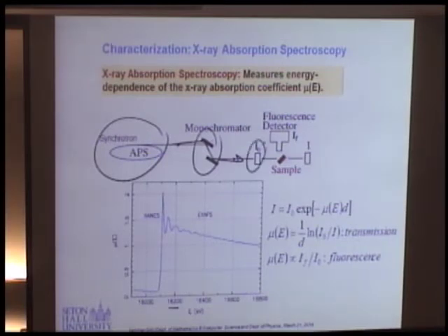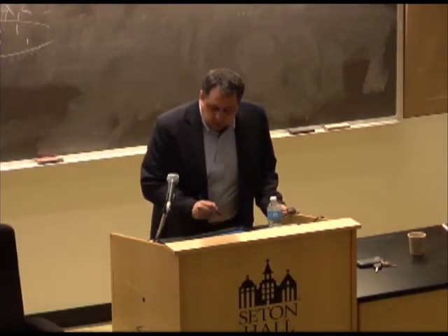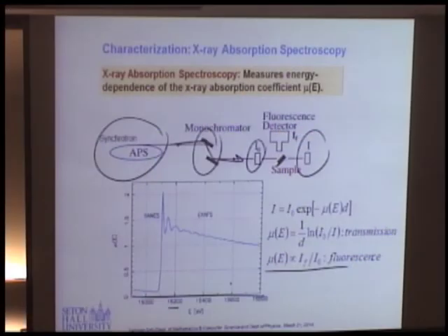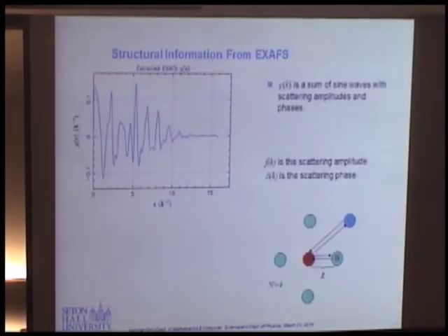You pass through a detector to measure the X-ray intensity, then through your sample, and then put another detector. Some of it is absorbed. So from the ratio of absorbed to incoming, you get the absorption coefficient. You tune the energy, and you get the absorption spectrum. If there is a nice crystal background, you get this wiggly interference pattern. Then you take that small part and do the analysis on it. This is a little technical, but we go from energy to momentum space.